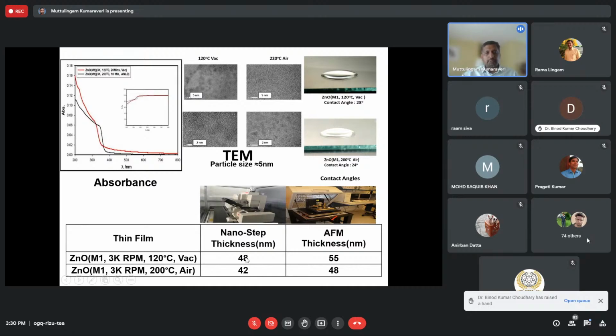same solution or same dispersion and same speed, but we get a little bit thicker film at 120 degrees, that is 6 nanometers more. But when we compare with the AFM, we use the AFM method to measure the thickness, and it is a little bit more. There are some issues. We just make a line or one scratch on the film, and we measure the thickness from the AFM. It might be some error. So it says 55 and 48. So we can see that 120 degree annealing gives a thicker film than this.